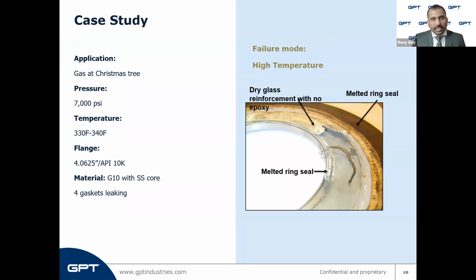Moving on, we can see a case study of how GRE gaskets fail in high temperatures. This is a live example to emphasize the risk of plastics being exposed to temperatures that they will not be comfortable with. This was a gas application at a Christmas tree. It was high pressures at 7,000 psi at over 330 degrees Fahrenheit. The gaskets were G10 with a stainless steel core. These gaskets were exposed to temperatures exceeding the rated value of G10 material.